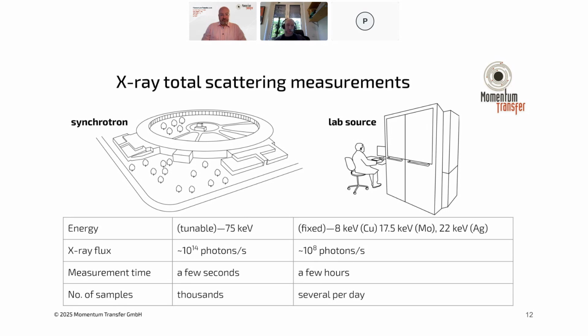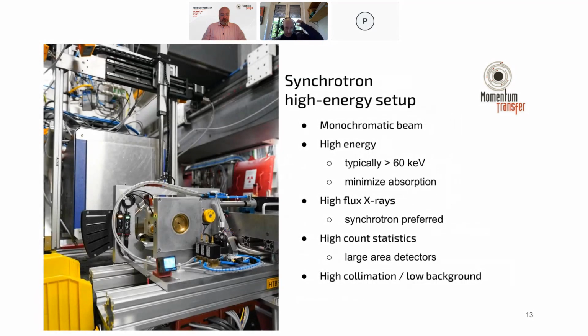And the other important thing, and I know I'm jumping all around this table here, is that we're working at much higher energies than what you have accessible with laboratory sources. So actually 75 keV, kiloelectron volts. And so this allows us to take advantage of a lot of benefits of that in terms of how we do the measurements and in terms of the quality of the data. And so I'll talk a little bit about that in a bit. So, the synchrotron high energy setup.